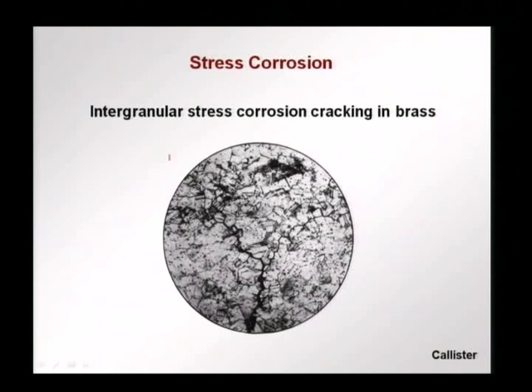In brass, this is how stress corrosion would look like. You see the grains, the small grains, this is a polycrystalline material, and at the surface of the grains, we have areas of higher energy, these are surface defects that we had discussed before, and when this material has some stress along with a corrosive environment, the crack starts to go along the grains through the grain boundaries and causing crack propagation and ultimately failure. So, this occurs due to the combination of the stress which is accentuated at the defects along with the penetration of corrosive material in the crack, leading to further crack propagation and failure.